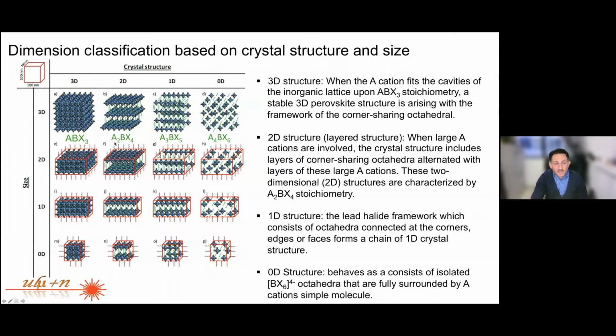However, when the A cations are quite large, the crystal structure includes layers of corner-sharing octahedra. You can see this case here. In this case we have two-dimensional structures, with layers of octahedra separated by other layers, and the formula is A2BX4 for the two-dimensional structure of these nanocrystals. And when the lead halide framework consists of octahedra connected at the corners or faces, we have a chain of octahedra, or a one-dimensional structure.